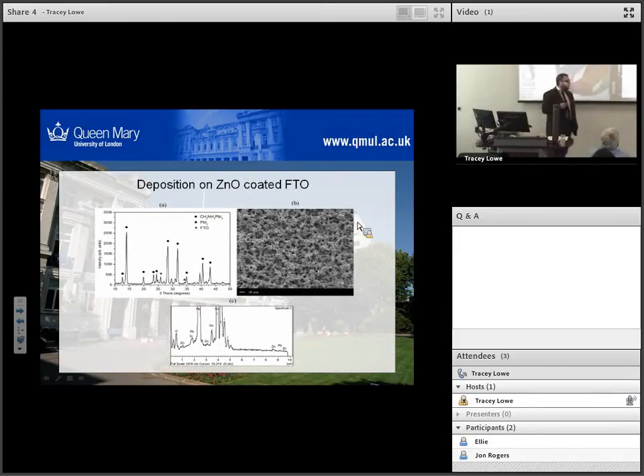Okay, so this is on FTO. It needs to be done on the zinc oxide layer really, because you need a blocking layer in your actual cell. Here, again we've got kind of porous microstructure, but actually much better coverage in terms of the coverage of our film.